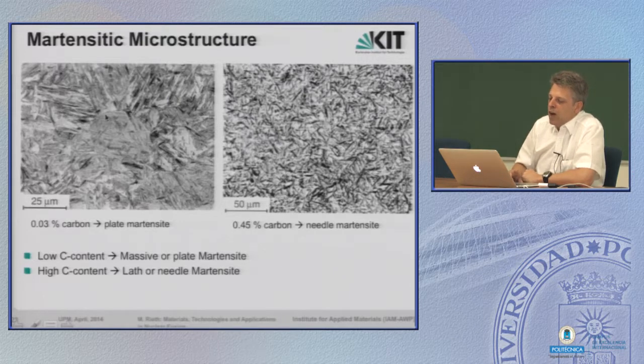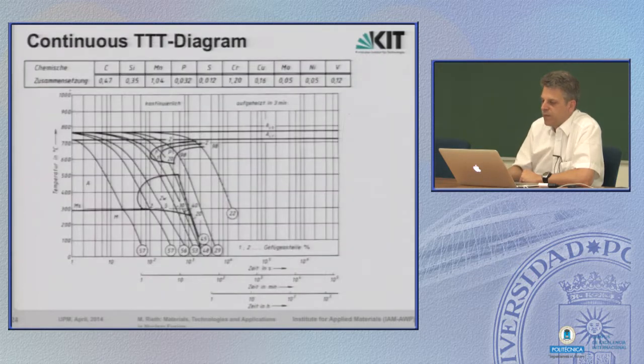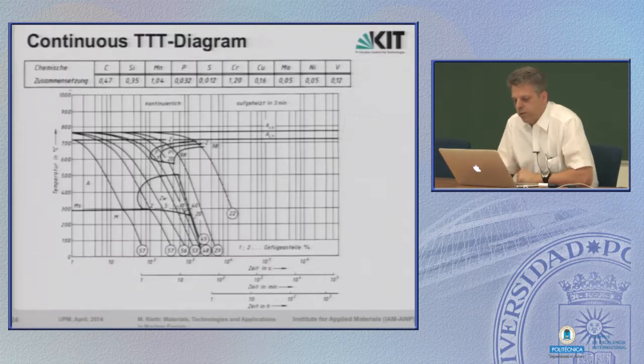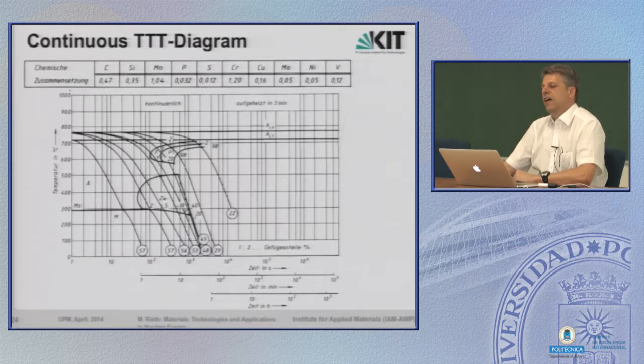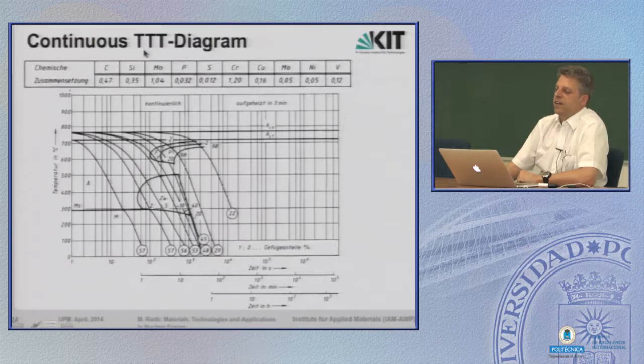If we have low carbon, then it's called plate martensite or massive martensite. If there is a much higher carbon content, then it's called needle martensite, or sometimes also lath martensite. That's the effect of quenching from the austenitic phase. If you buy a steel from a manufacturer, he provides this steel with a diagram, a continuous TTT.